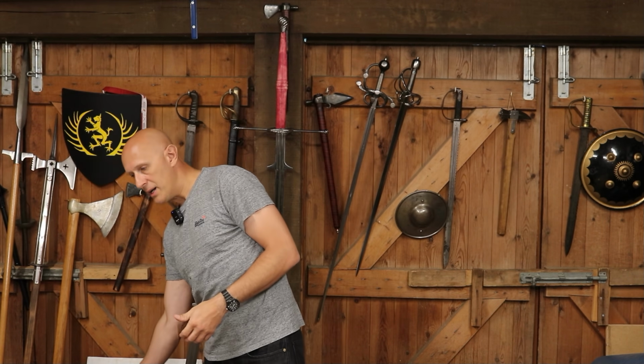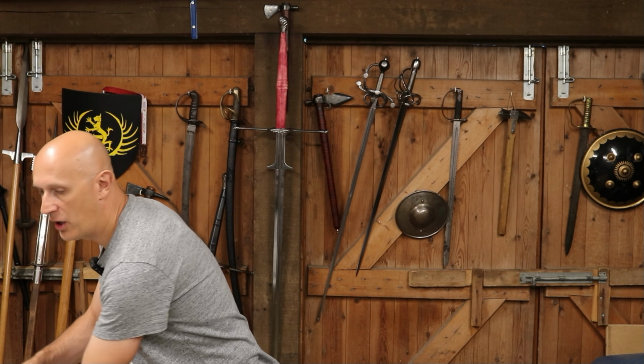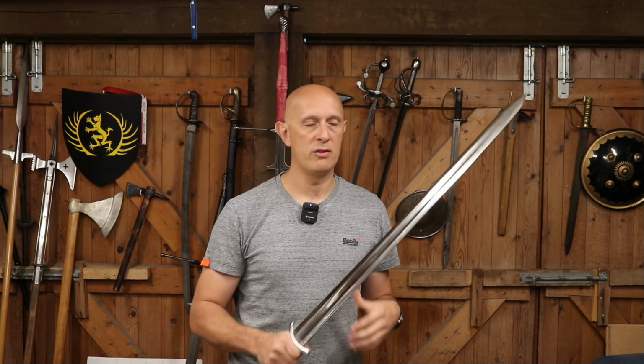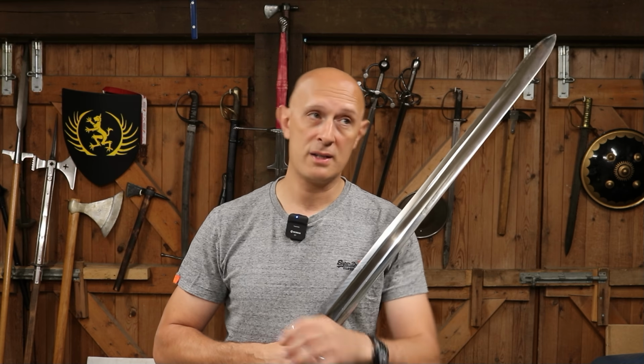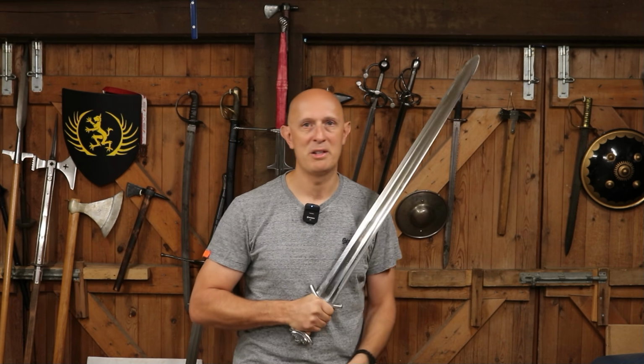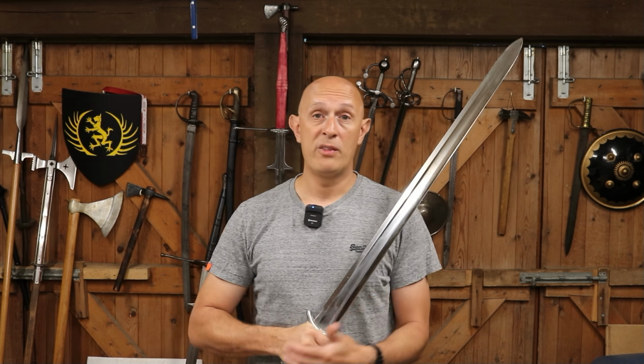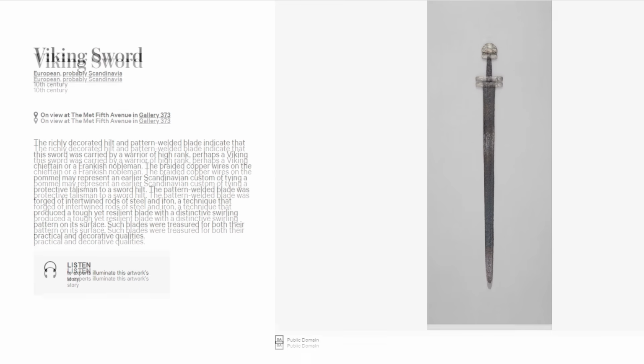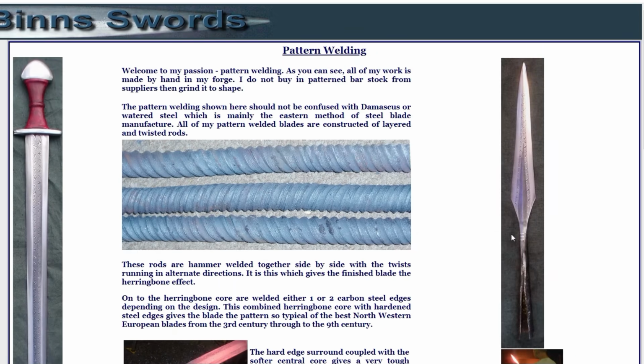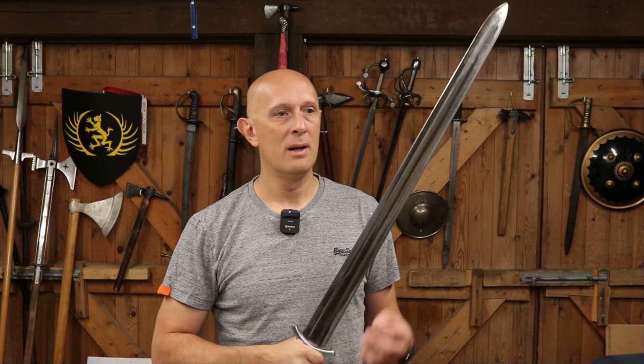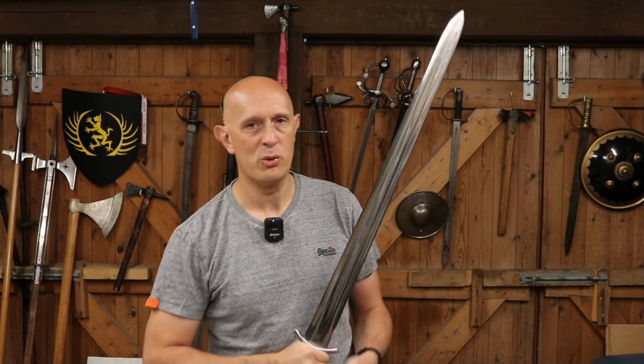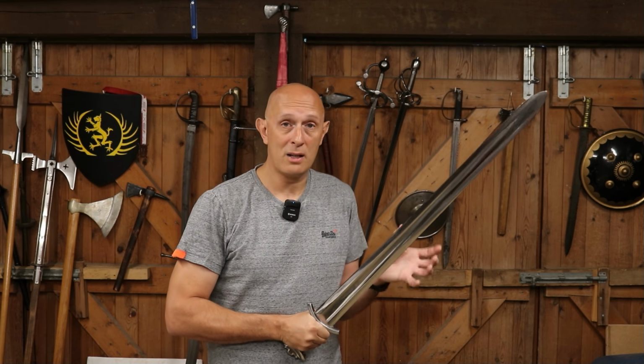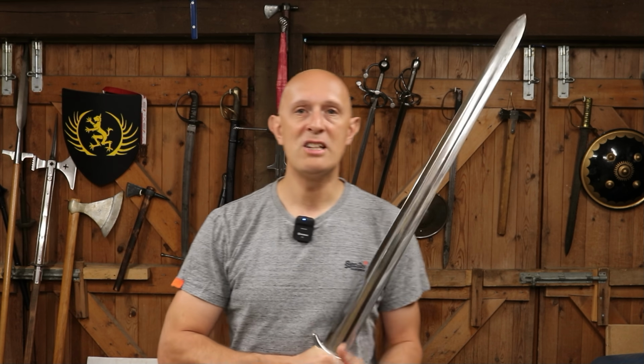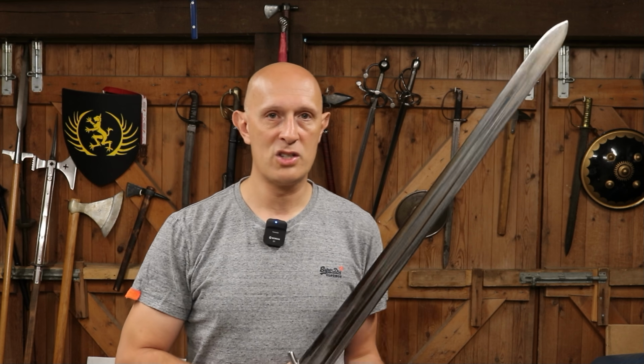We don't know. But what is interesting is if we go back into earlier medieval periods, we start to find the steel, generally speaking, is of less reliable quality, except if we're talking about Ulfbert swords, but let's ignore Ulfbert swords because they're a bit of an outlier. And what we find is, when you get back into the pattern welded period, you've essentially got a pattern welded core of different types of iron and steel, some of which might not be hardenable. So if you've got particularly low carbon steel mixed in the pattern welding in the centre of the blade, when you quench your blade, even if you quench the entire thing, the centre might not harden very much or hardly at all. Whereas the edges, made of higher carbon steel, will quench, will harden. So you do end up with a blade that might have hard edges and a soft core.